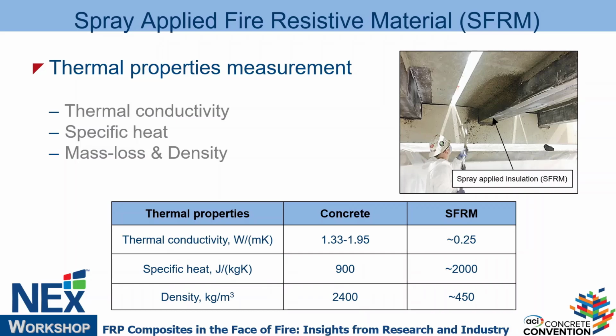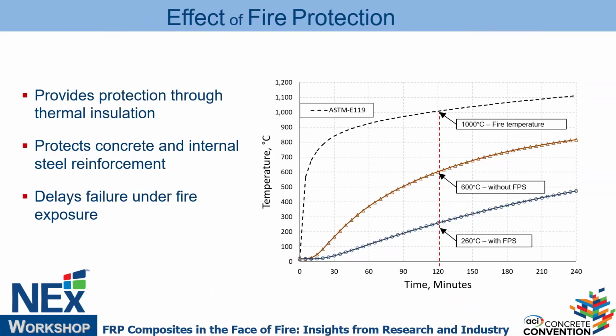This is one of the systems that we use, and you can see most of these systems have much lower thermal conductivity. SFRM stands for spray-applied fire resisting material. Thermal conductivity, you can see it's much lower. Specific heat is higher, which means you need more energy to heat the elements, right? So it's a good thing to be higher. And the density is much lower because there is lots more air in it, and air is a good insulation. And the materials that provide insulation, vermiculite and other things, are embedded within it, right?